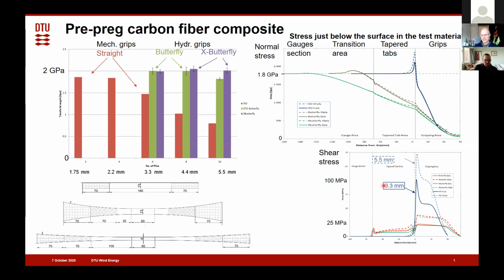But what is more critical, I think, is, so here this is a stress value. If you look at the shear stresses at that region here, the dashed line here is the thick one and the solid line is the thin one. You can see that we have rather high shear stresses near the end of the grips. And that's for all cases, so also for the butterfly and for the extended butterfly, we have larger shear stresses because that's the only way we can introduce the load from the grips into the test material. And we can see that the load levels for the shear stresses are quite high compared to, I would say, expected shear strength of the composite.